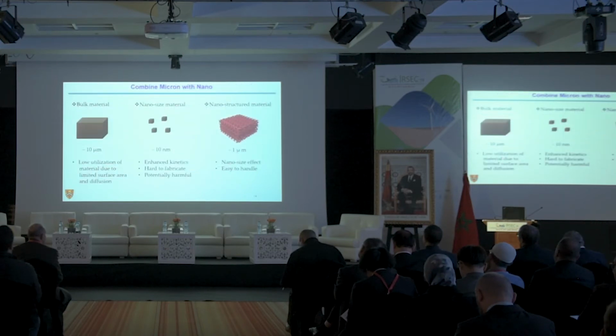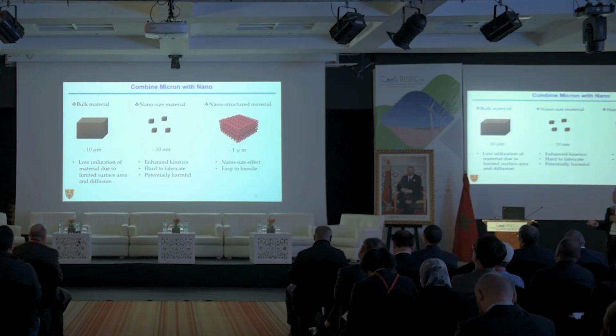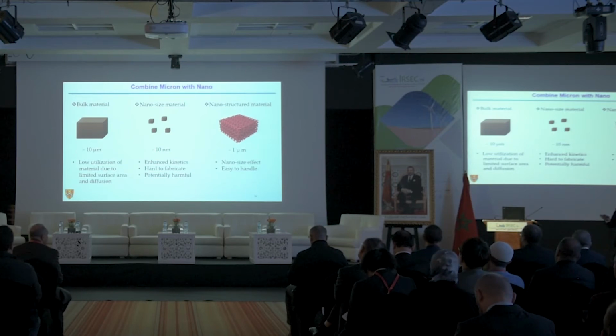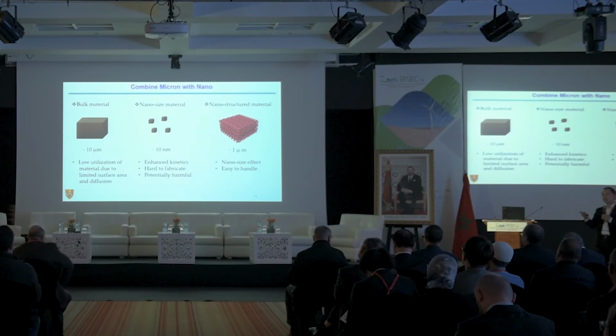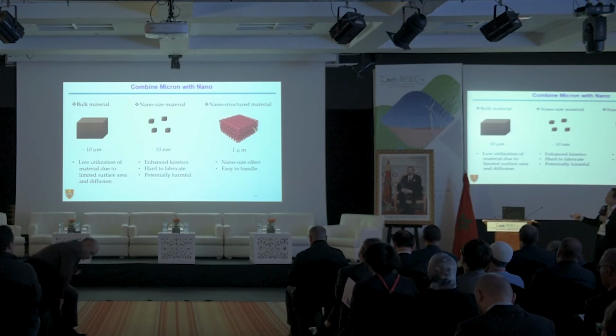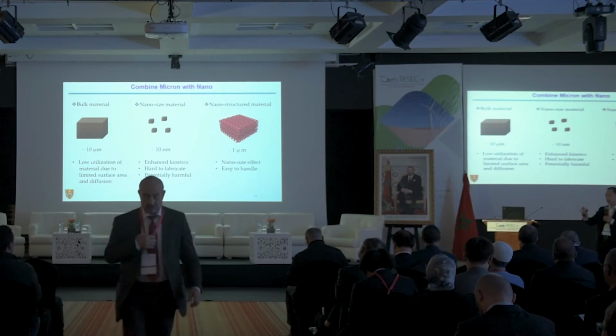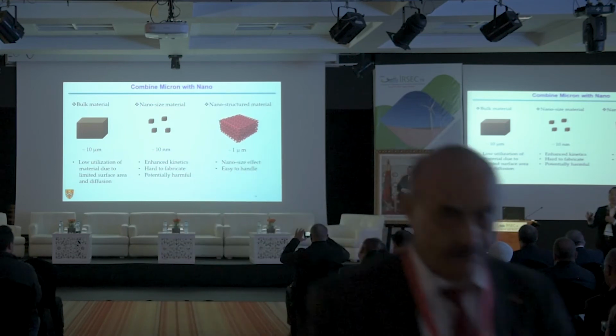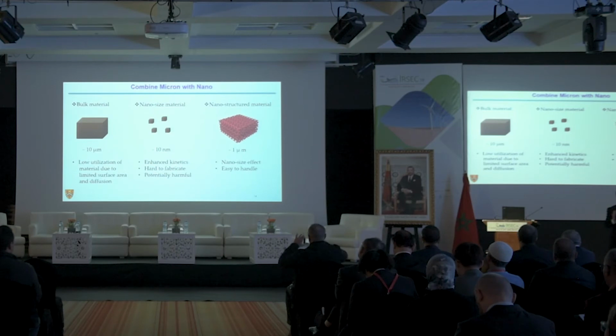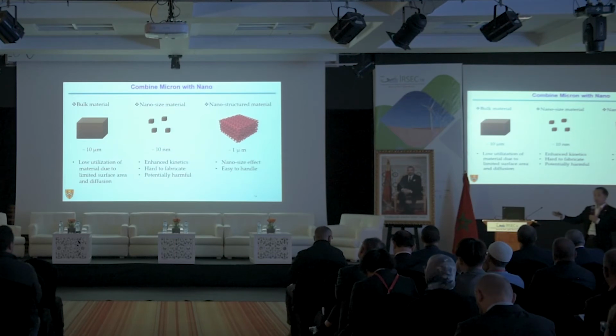So when we try to design this catalyst, at the beginning, what is available is always bulk materials. However, as we know, bulk materials don't have a high surface area, so we need to go to nano. When we go to nanomaterials, when we try to use them, we found that it's not easy to fabricate into the electrode. So finally, we have to combine these into nanostructured materials. These nanostructured materials still look like particles, but the particle size will be more than micrometer size. So it's easy to fabricate an electrode. However, it still has high surface area so that you can meet the requirement for the catalyst.